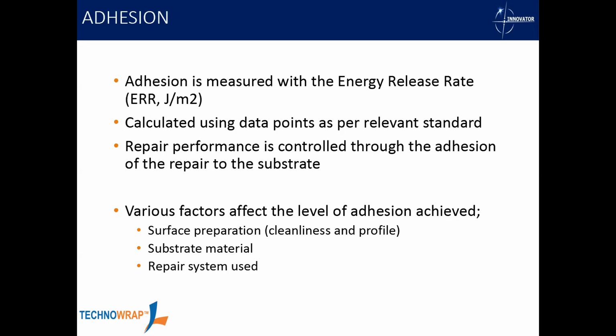And as I said, the repair performance is controlled through the adhesion. The more load you can transfer through that bond line, the better the composite will be. And there's a few factors that actually affect the level of adhesion. One of them is surface preparation, which we've had a few questions on. So that comes down to the cleanliness and the profile that's achieved. I've got a slide on that next.